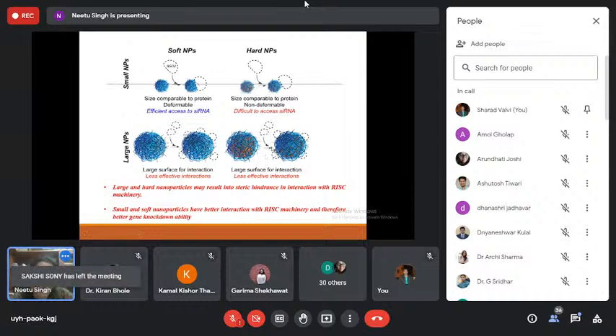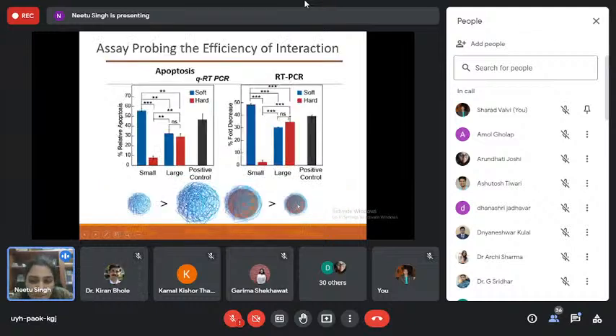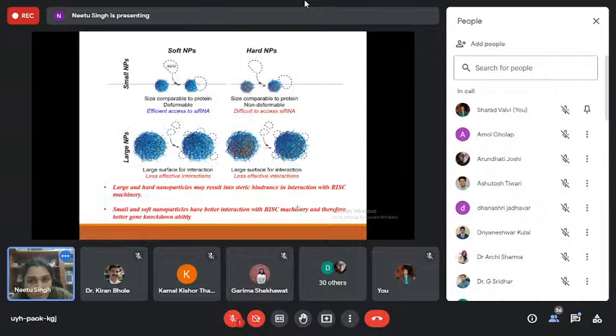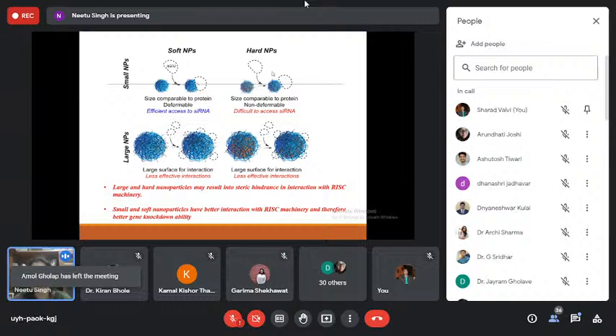Whereas if you have a hard particle, so if you go here, this was worse because it is small in size. There are not enough sites where it can interact, and it is really, really hard. It cannot deform. So the worst is a hard nanoparticle which is small in size. This information, with our hypothesis, we could have never obtained, okay? Because we never understood that it is making almost like a flower structure. So we did cryo also. I'm skipping all that data here, but we did a lot of confirmation of this aspect.